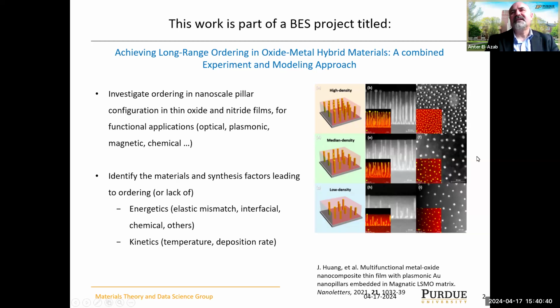Haiyan is the one who grows these films and characterizes their properties. We, as collaborators doing theory and computational work, are trying to understand how these things grow and what gives rise to the self-organization of these pillars in the matrix of the film. Just to let you know the order of dimensions here, the film thickness is from here to the top. This is on the order of 20 to 30 nanometers, maybe 40 nanometers or so. These vertical lighter colors are the pillars. The dark background is the matrix.